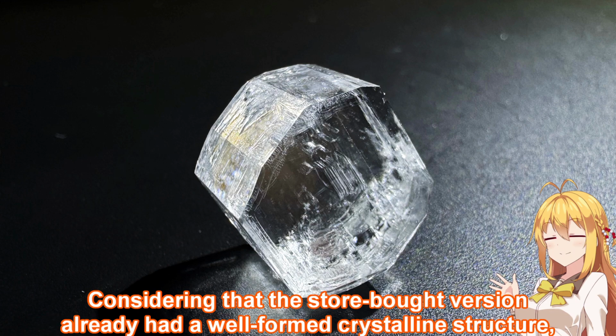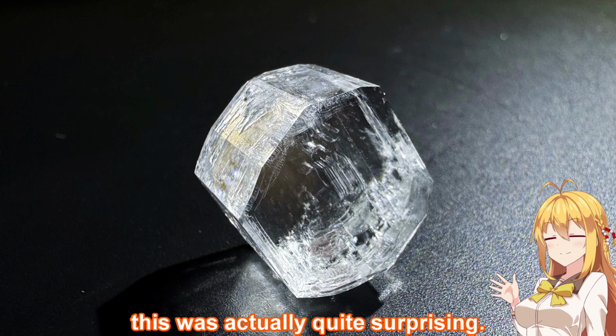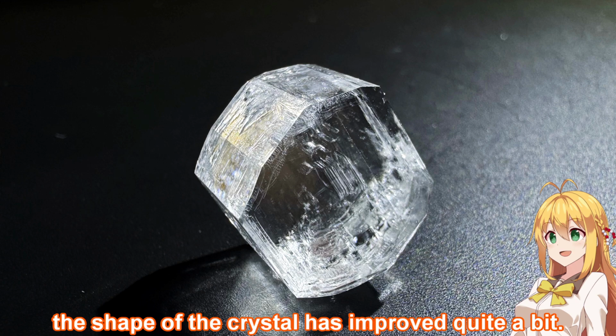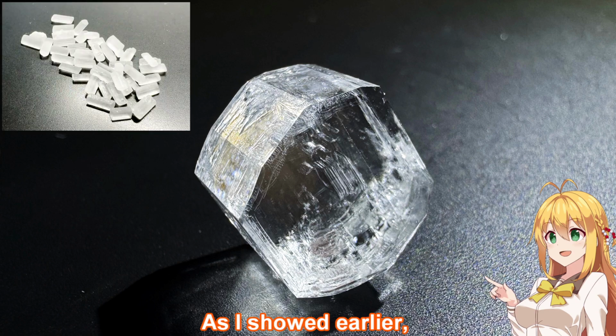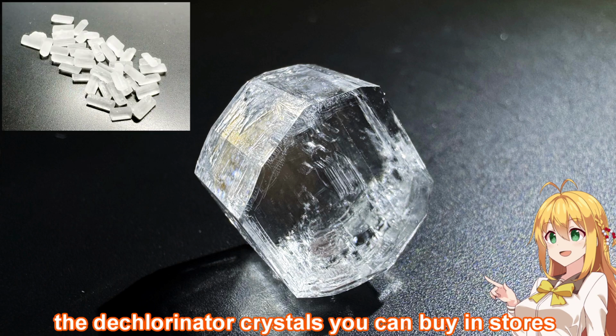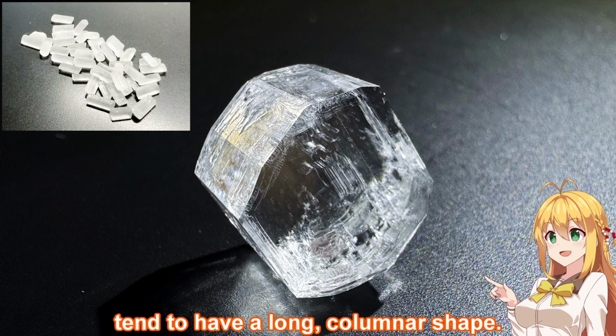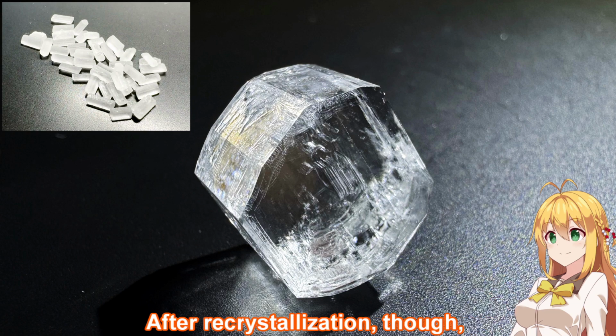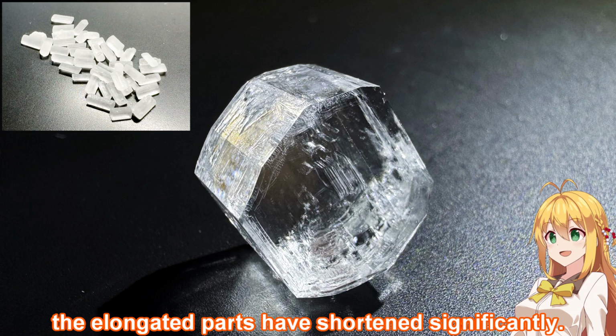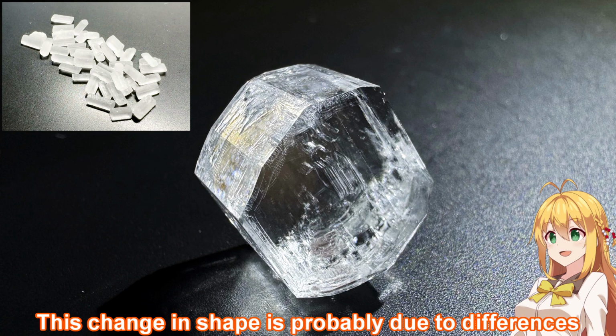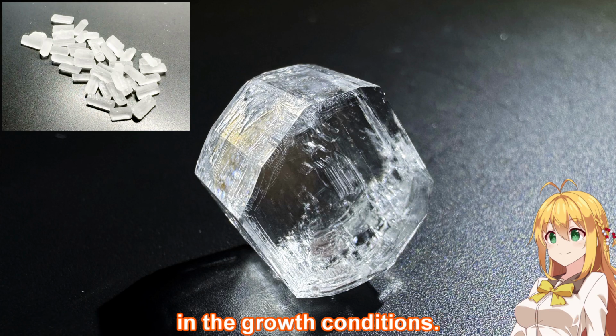Considering that the store-bought version already had a well-formed crystalline structure, this was actually quite surprising. On the other hand, the shape of the crystal has improved quite a bit. As I showed earlier, the Dechlorinator crystals you can buy in stores tend to have a long, columnar shape. After recrystallization, though, the elongated parts have shortened significantly. This change in shape is probably due to differences in the growth conditions.